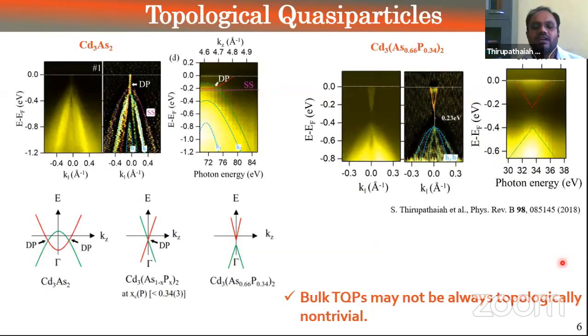So in fact, unlike what I said, surface Dirac points or Weyl points, whatever it is, these three-dimensional or what you call bulk Dirac points are not always topologically non-trivial. So we found one such case. This was a famous 3D Dirac point. Here you can clearly see a gapless Dirac point, and when we dope, it's not even doping, it's just disordering, like replacing arsenic by phosphorus, which is an isovalent substitution, and there is a gap opening clearly.